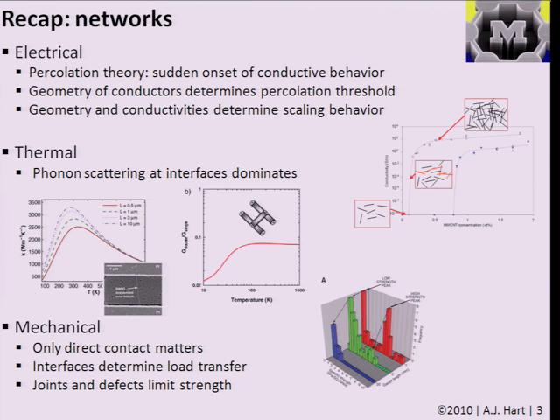We talked briefly about thermal properties—a complex issue somewhat beyond our scope—but we saw dramatic differences in thermal conductivity for individual nanotubes versus tightly packed nanotubes with many junctions. This emphasized that scattering of phonons in networks of nanostructures is often a dominant attribute of the assembly's thermal conductivity. While one carbon nanotube could have a thermal conductivity of about 3,000 W/m·K—nearly as high as diamond—a well-packed tangled mat had a thermal conductivity less than that of some typical polymers.